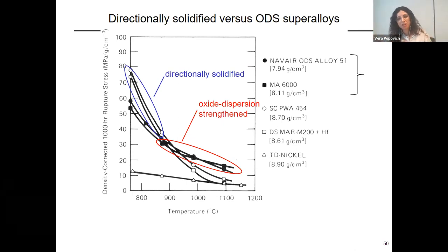What happens after 900 degrees is that you have coarsening or dissolution of gamma prime. So with temperatures above 900 degrees C, if the alloys are used for this kind of temperature application, and we also see this kind of alloy used for nuclear applications, the yttria oxide dispersion strengthened alloys are then used. They do not show this kind of deterioration of properties.